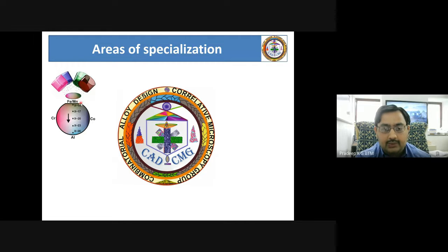For example, in this case, you see if you have an iron manganese target on one extreme and aluminum on the other extreme, you can get a uniform variation in composition as you move from top to bottom. Similarly, if you move from left to right, we get a uniform gradient in composition in the chromium to cobalt rich region. That means in one material synthesis process, at one step, we are able to cover a large scale of composition variation. And depending on the composition variation, we will have different phase formation and microstructure, and therefore very different properties. Now, this is one aspect of non-equilibrium phase formation in the form of thin film. And a similar combinatorial approach we also do on a bulk scale.